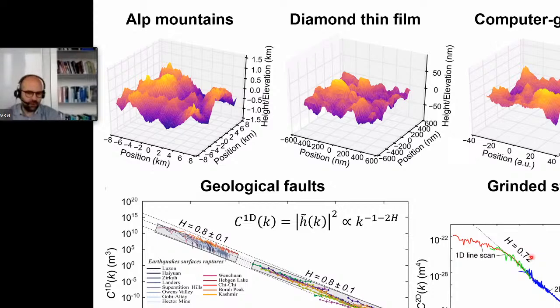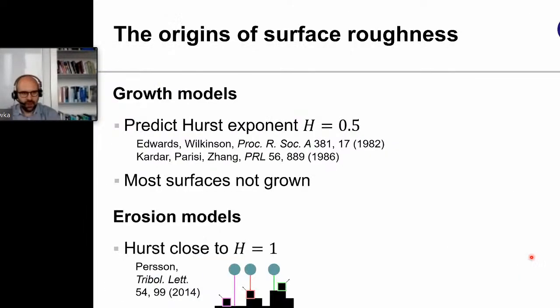So why is this the case? What are the origins of surface roughness? I mean, there's different things that have been done in the past. There's a lot of work in the literature actually on surface growth. So if you think about CVD or PVD growth, there's growth models that physics communities have looked at. They do lead to self-affine surfaces, often with a Hurst exponent around 0.5. The two most famous models are probably the Edwards-Wilkinson and Kardar-Parisi-Zhang model.